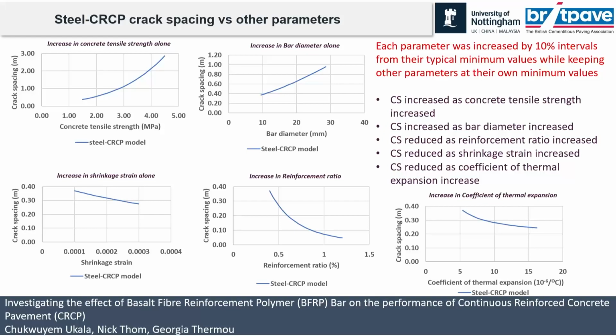But we could also see, for example, if you look at the direct tensile strength, the change in crack spacing from here to here gave us a wider range. It told us that within the 200%, because we changed it by 10% up to 200%, each of them gave a change, and the concrete tensile strength gave the highest change. That gave us the idea that the concrete tensile strength was the most influential in affecting the CRCP using the models that we had selected. We also saw the same for the bar diameter, before the reinforcement ratio. So it went from this, and this, before the other two.